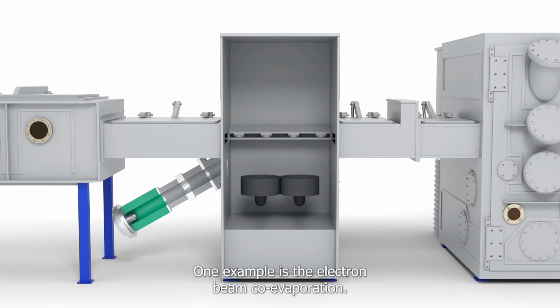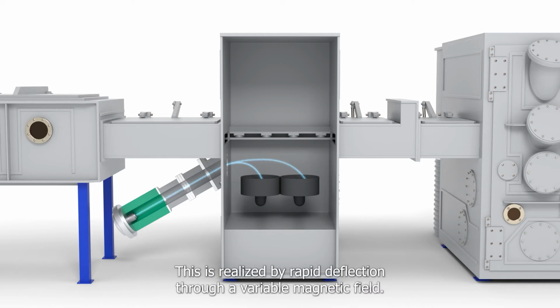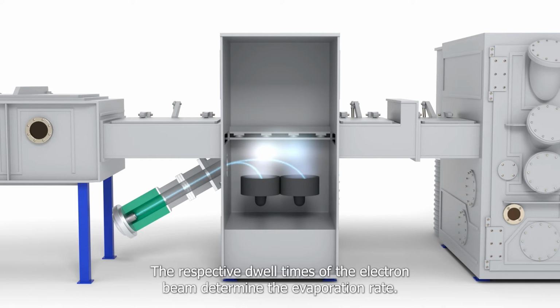One example is the electron beam co-evaporation. Here, 2 crucibles with different evaporation materials are used. The electron beam jumps between the 2 crucibles. This is realized by rapid deflection through a variable magnetic field. The respective dwell times of the electron beam determine the evaporation rate.